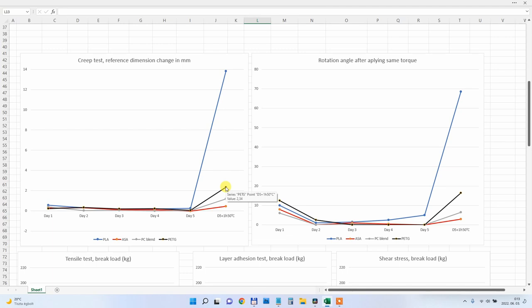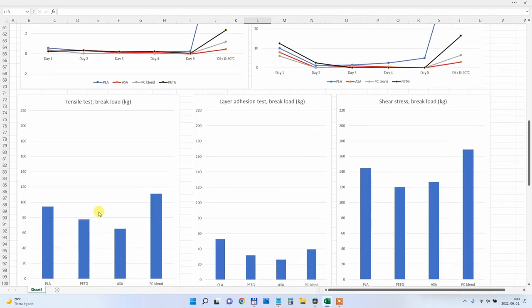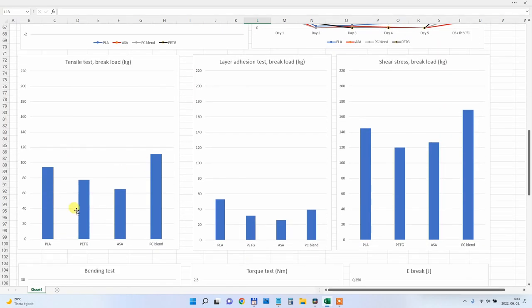And then you can see this is the PETG, and interesting that PC blend and then ASA. So ASA is better in this creeping compared to the PC blend. On the tensile test, the PC blend was the strongest, then PLA, PETG, and ASA was quite disappointing in this test. And similar is with the layer adhesion test.